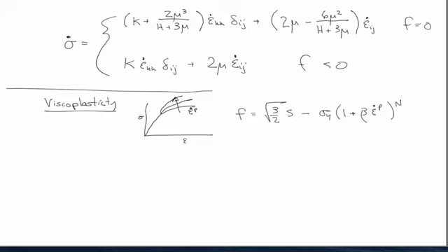So now you have the quasi-static yield stress here. You have an additional parameter here, and you have an additional parameter here. And so these are fitting parameters that fit this sort of response curve that looks like this. Okay? Well, if we work through the same sort of details we did before, now I'm going to differentiate this guy with respect to time.